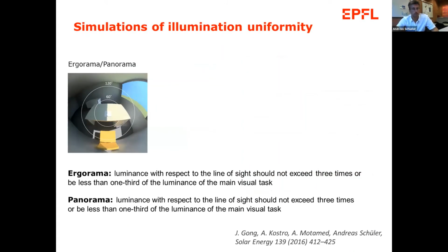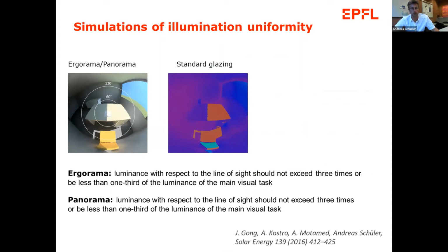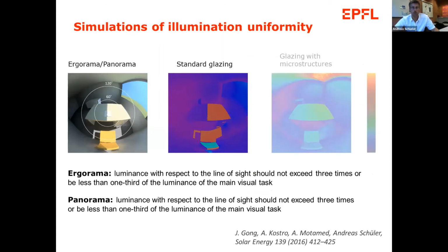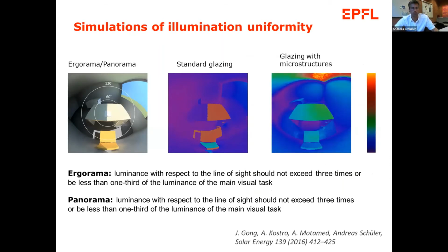We also care about visual comfort. So we need high visual comfort for both ergorama and panorama. So ergorama, we would call the 60-degree cone here ergorama and the 120-degree cone here panorama. And we would like to avoid excessive contrast differences, especially in the ergorama. So our simulation says that for standard glazing, we have many situations where this high contrast situation occurs, while for the microstructured glazing, we have a much more homogeneous illumination of the work plane. So it's also a good advantage.